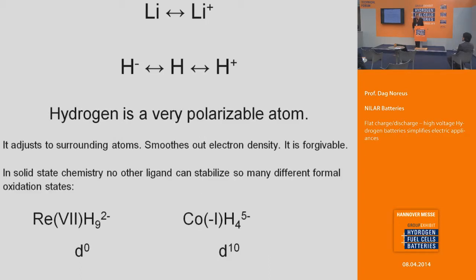First we can look at some philosophical way to look at lithium and hydrogen. So lithium is usually metallic, zero valence state, and plus one it can be. Hydrogen on the other hand is a very polarizable atom. Polarizable meaning easy to distort the electron cloud. And it's in a way to store electrons. I mean, the chemical energy you get out of the battery is when those loose electrons on the hydrogen sort of fit into the octet on oxygen. This is more or less common to all batteries.